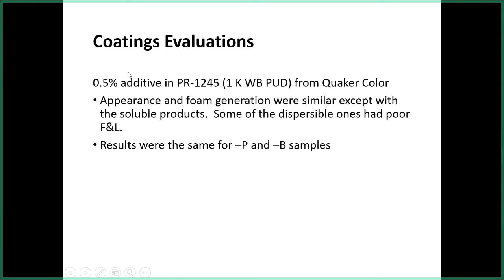So we also did some evaluations in coating systems. First, we did 0.5% in a waterborne polyurethane dispersion. And it's important to note that the appearance, the flow and leveling, and the foam generation are all very similar. Although some of the products we chose had poor flow and leveling, they had it with both the petroleum and bio-based versions.